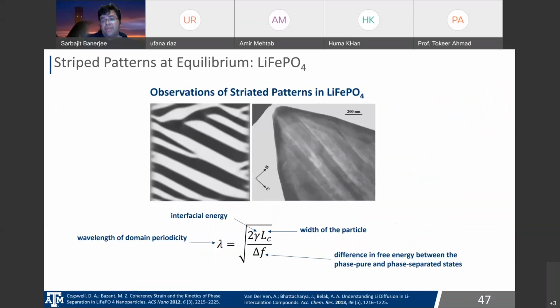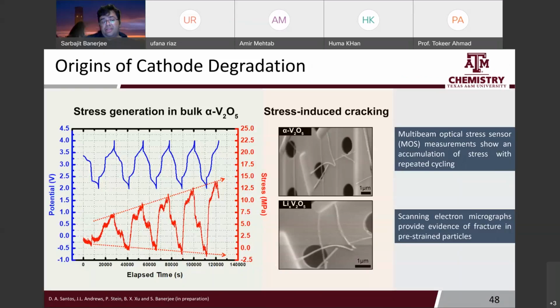And these stress gradients over a period of time will actually be manifested in this. And this is a measurement we've done with Matt Farr's group at Texas A&M, where we see the accumulation in stress of a full cell with cycling because of these electrochemistry mechanics coupling. And this is actually a beautiful image that David Santos has taken showing a bent wire that actually gets cracked after a couple of cycles.